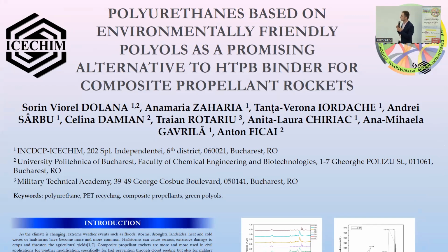For this, we compared the HTPB with polyurethane formulations based on commercial polyether polyols and a novel green polyol synthesized in our laboratory by chemical recycling of PET, polyethylene terephthalate. We also used glycerol as a cross-linking agent and castor oil both as a cross-linking agent and as a plasticizer, being a trifunctional polyol.